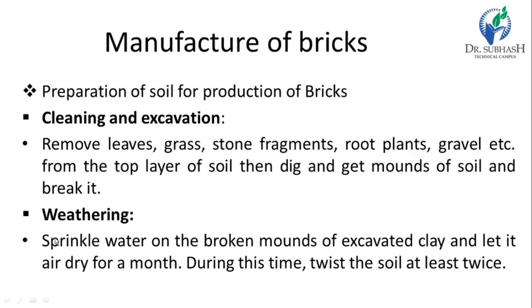Next is weathering. Sprinkle water on the broken mounds of excavated clay and let it dry for a month. During this time, turn the soil at least twice.